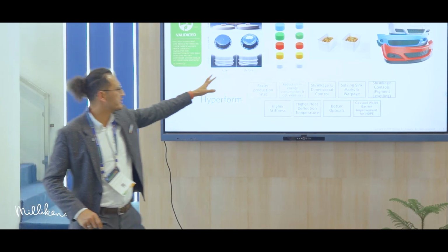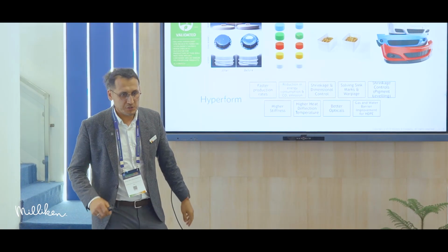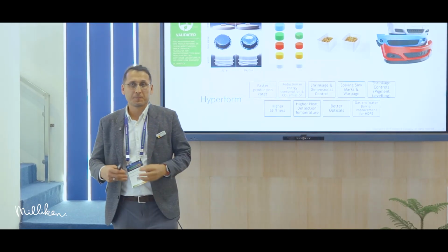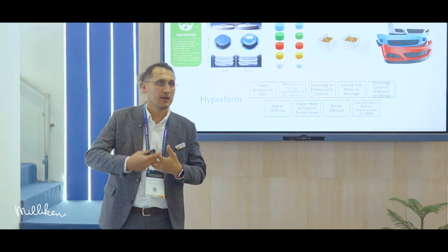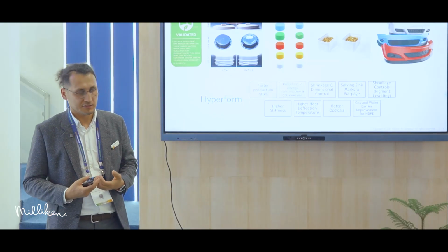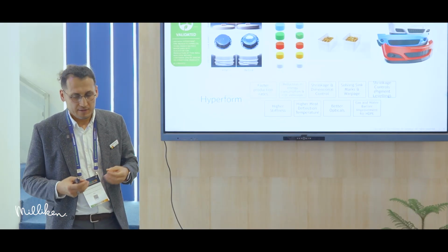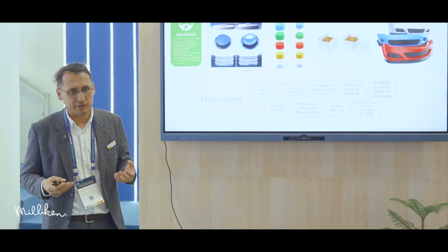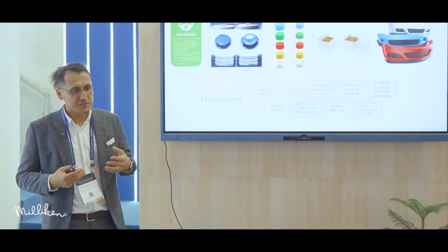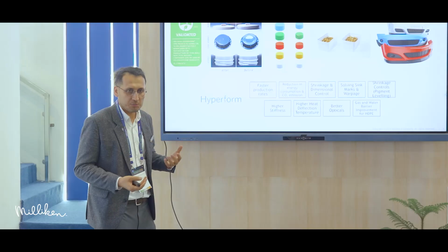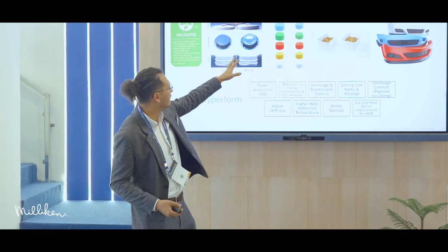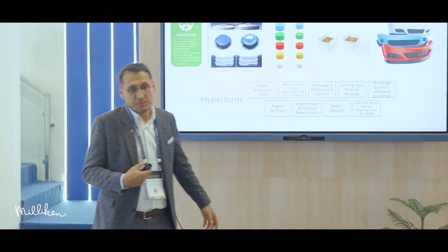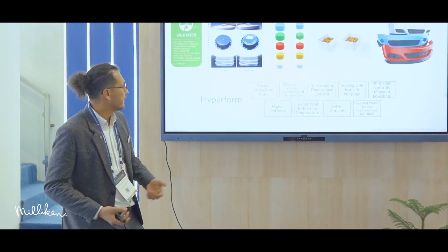This is related to TC. When the nucleator is being used in the caps enclosure, if you have a blue pigment inside, especially blue or green colors, blue pigment itself works as a nucleator as well. It's just not a good nucleator, but it works as a nucleator. So it starts to outperform your own nucleator, and then you have a different shrinkage when you have a different color of caps. In a production, that's what you don't want.